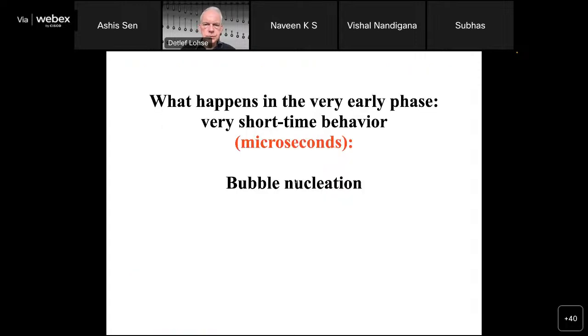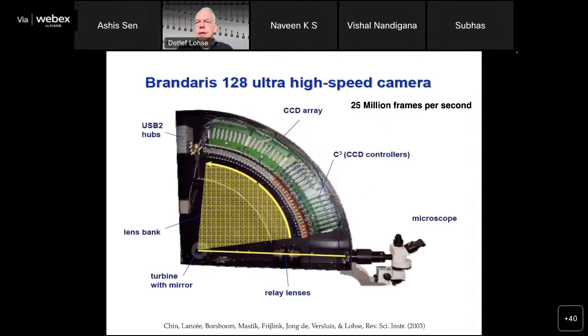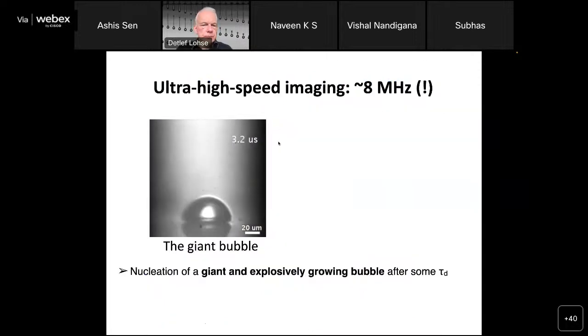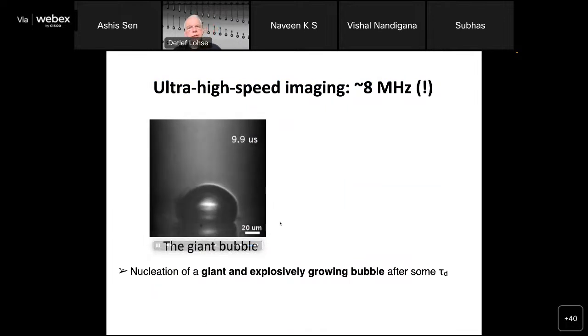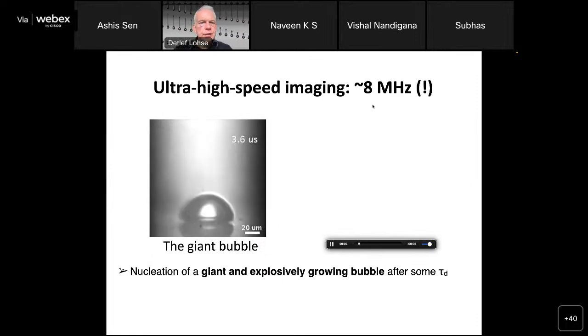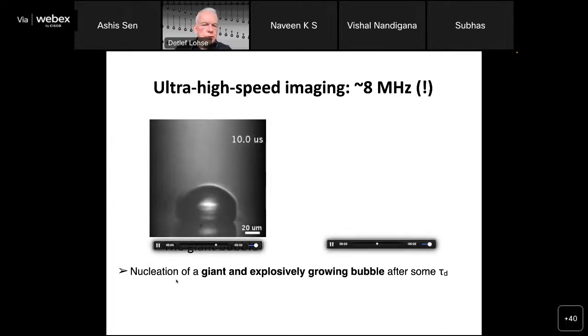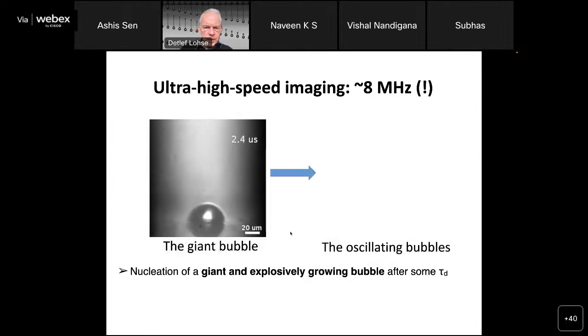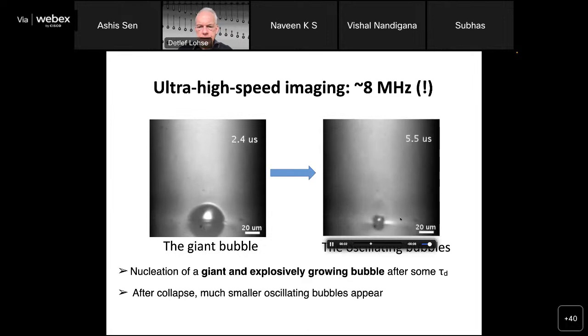And this is what I would like to show you now, which I think is the most interesting thing. So what happens in the very early phase at very short time scales? So it's microseconds. First I talked about seconds, then about 100 milliseconds, but now I go to microseconds on bubble nucleation. And we are pretty much the only ones who can look into this because we have this high-speed camera with 25 million frames per second, and we can really look at the very, very early phase. And this is what we see. We see this giant bubble generation here. Here we visualize it with 8 megahertz, 8 million frames per second. And then we see this huge giant bubble at the very beginning. And later we get some oscillating bubble here. I won't go much into this, but I would like to go into what's happening.